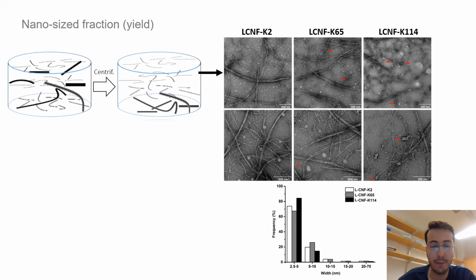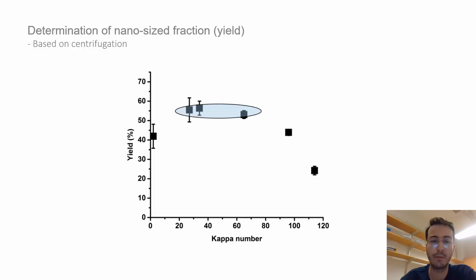If we separate the supernatant fraction and dry it, then from the mass of supernatant fibrils relative to the whole, we can calculate the nano-sized fraction or yield. When we calculate the nano-sized fraction yield, this plot occurs, and you can see that in the middle range of kappa number the yield is higher. I want to draw your attention to this special sample, kappa 65, because it has quite a high amount of lignin and still it has quite a high nano-sized yield.